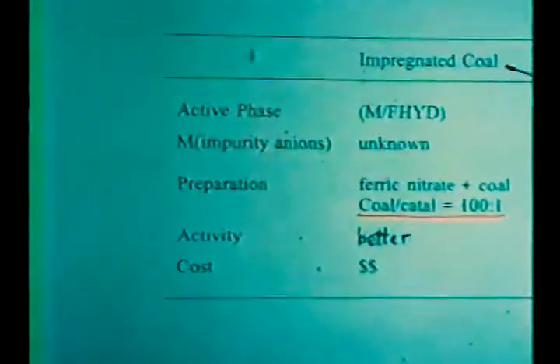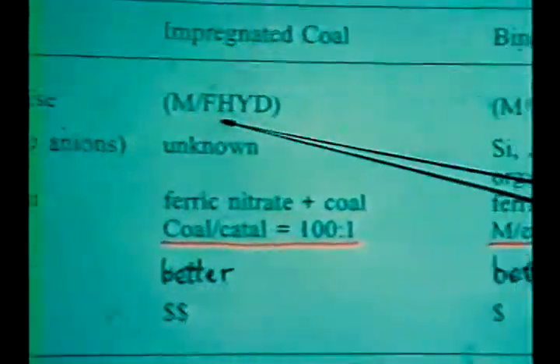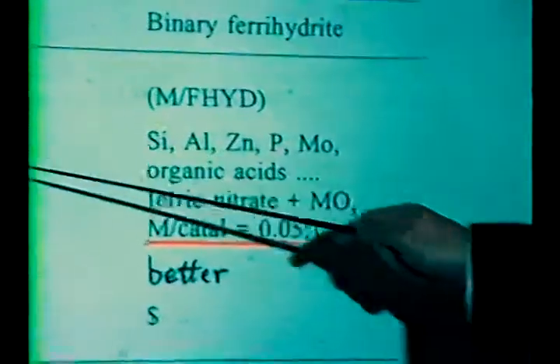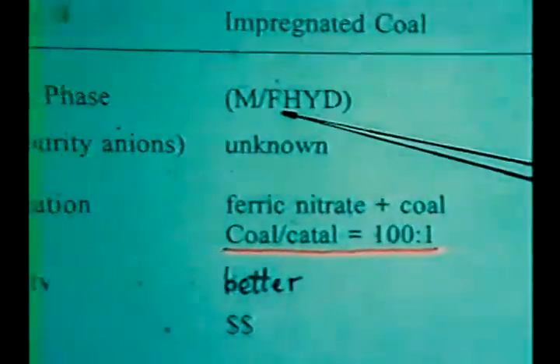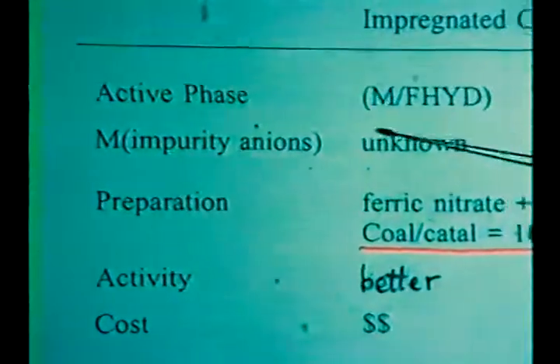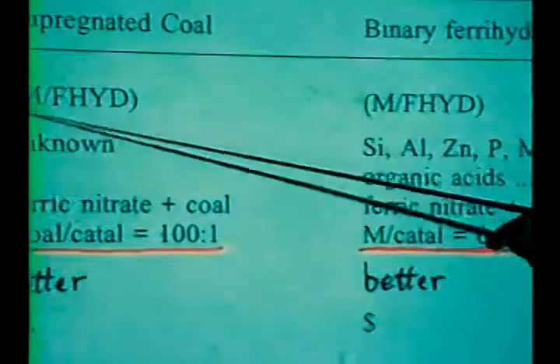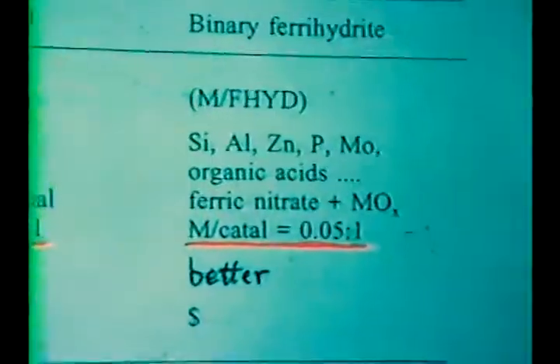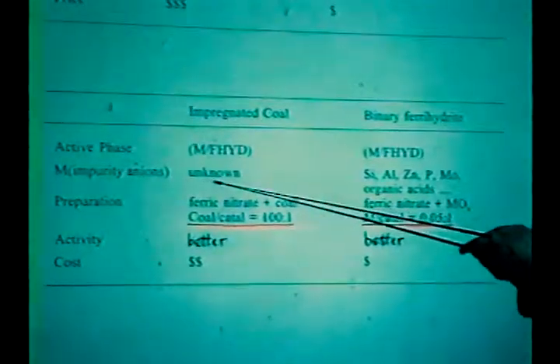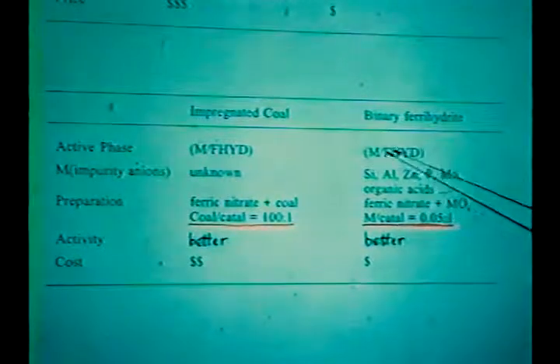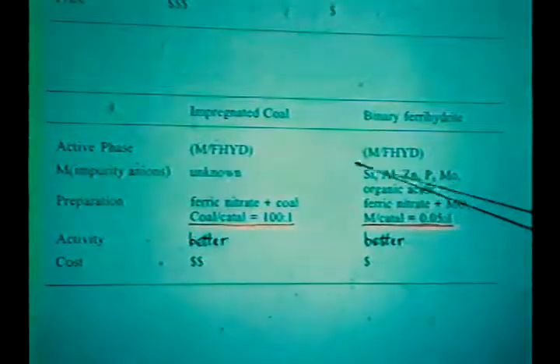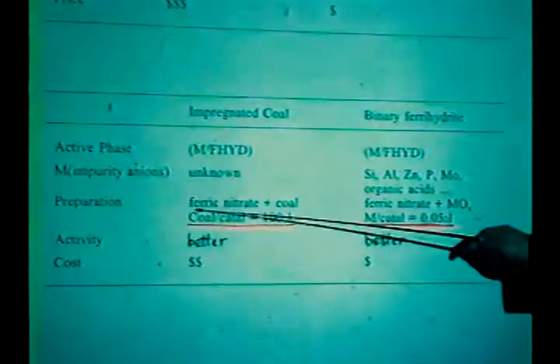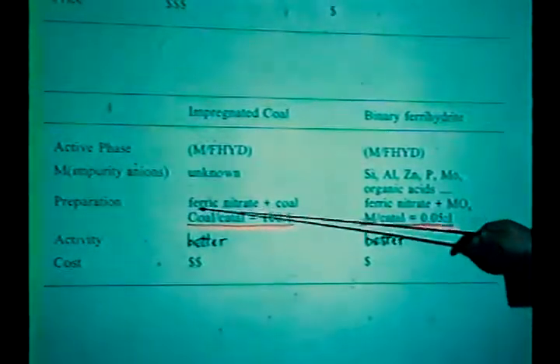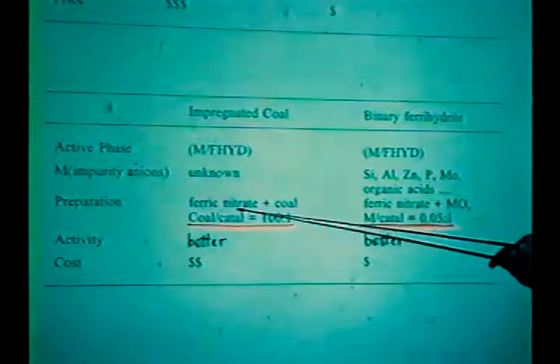Now we compare the catalyst we prepared with the impregnated catalyst. The active phase, as I've shown you, both are finally ferrihydrite oxide, because the iron ferrihydrite surface is covered by impurities. What is in the impregnated catalyst, we don't know, but here we can control it—we can put all kinds of second elements at the surface. In preparation, they both use, first, they put coal into ferric nitrate solution.